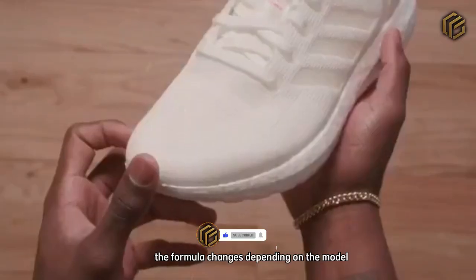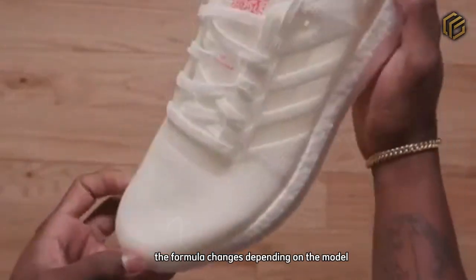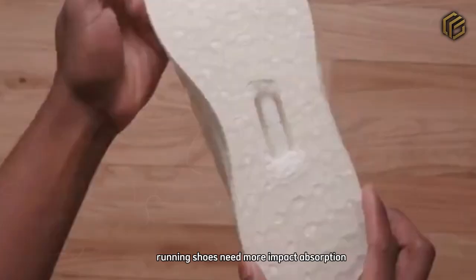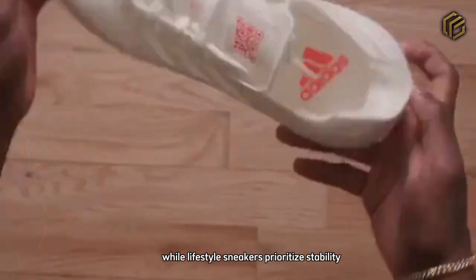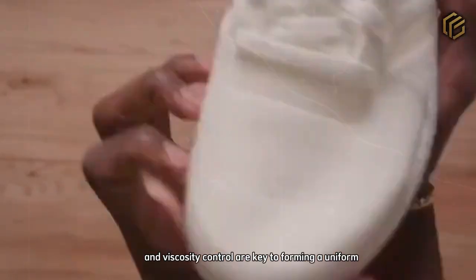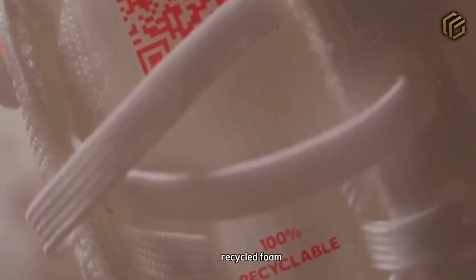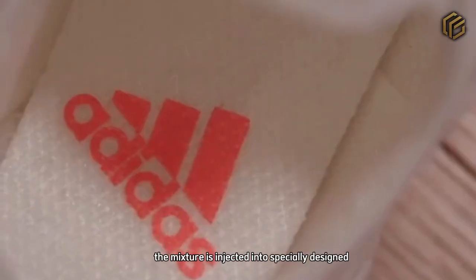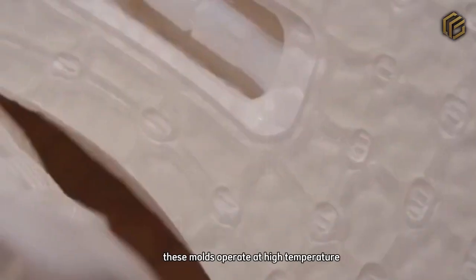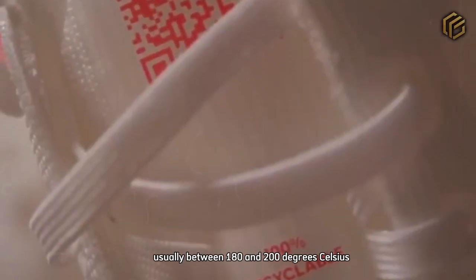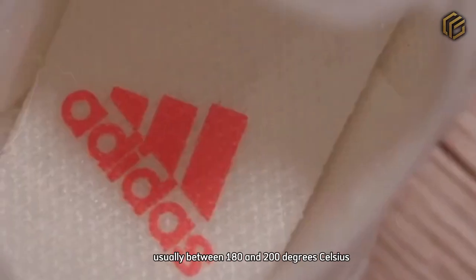The material is ground, filtered, and mixed in high-pressure tanks until it reaches the ideal density. The formula changes depending on the model. Running shoes need more impact absorption, while lifestyle sneakers prioritize stability. Temperature and viscosity control are key to forming a uniform recycled foam. The mixture is injected into specially designed metal molds. These molds operate at high temperature, usually between 180 and 200 degrees Celsius.